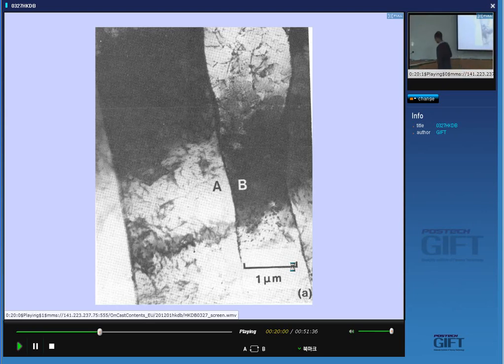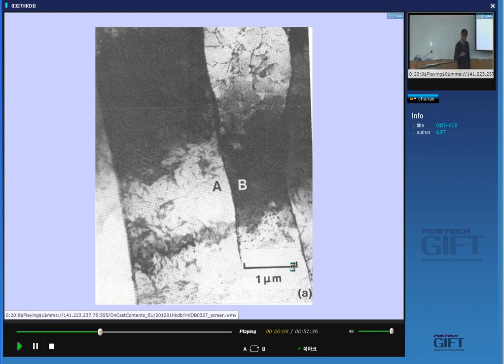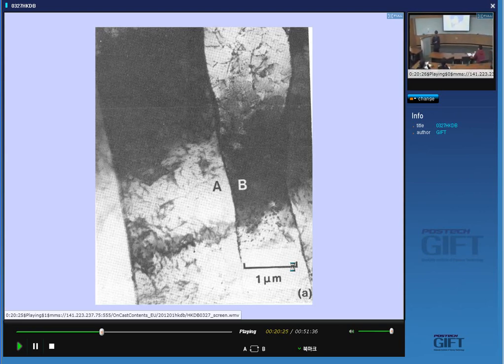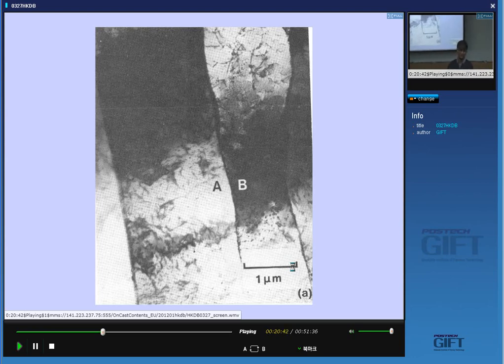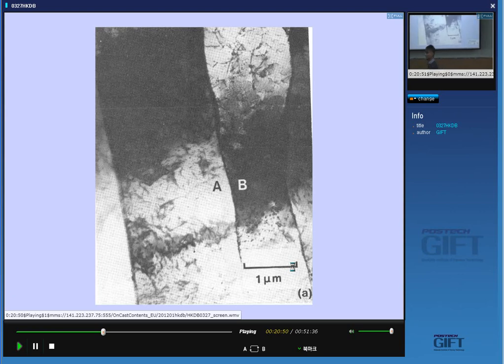That also explains the wedge shape: this plane is different from this plane — the crystallographic variants, meaning the same indices arranged in a different way — so there will be a finite angle between the two planes, and that is the reason why you get a wedge shape. When we look at this in a transmission electron microscope, we predict that there should be a single low-angle boundary between the two plates, and indeed that's exactly what you see. The scale is coarse — we were talking about quarter-micrometer for bainite — and here is a small low-angle boundary between the two plates which form optically as a single plate of Widmanstätten ferrite.